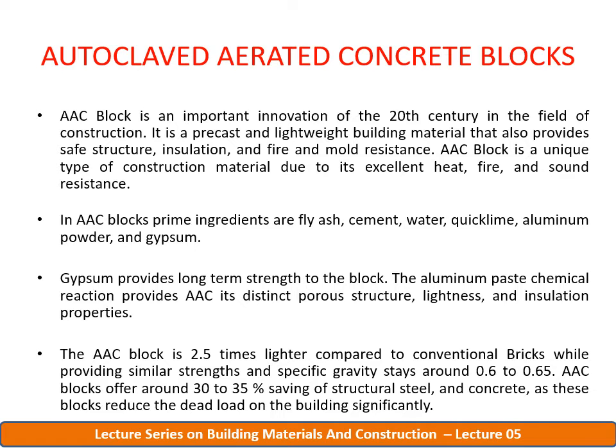These type of blocks are 2.5 times lighter compared to the conventional brick, while providing similar strength and specific gravity around 0.6 to 0.65. Autoclave aerated blocks offer 30 to 35% saving of structural steel and concrete as these blocks reduce the dead load on the building significantly.